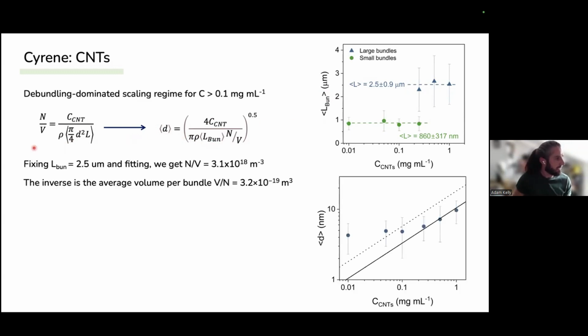So by fitting the data that we have here, this is the same data again, just on a log-log plot of the diameter versus starting concentration, we fix L bundle to be 2.5 microns, and this is the solid line here. It gives us a number volume of 3.1 by 10 to the 18 bundles per meter cubed. So the inverse of this value would be the average volume taken up by a single bundle, and this is this volume here, 3.2 by 10 to the minus 19.